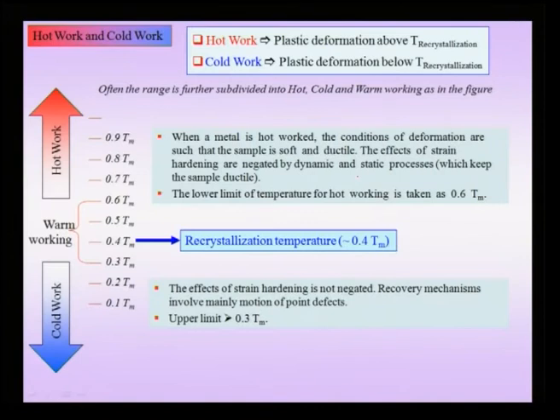Now, we are right in a position to define what is cold working and what is hot working, and further what we can call warm working. Because now we have a correct platform to define these terms: if you do plastic deformation above the recrystallization temperature, this is called hot working. That implies that the material can spontaneously recrystallize as the deformation is taking place, and that the material constantly remains soft and its ductility is not lost while working is taking place.